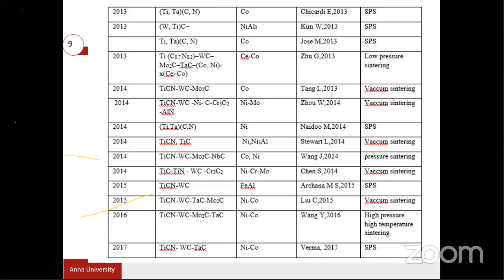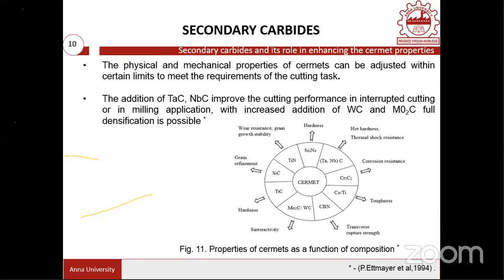Still, the problem faced by these titanium carbonitride based CERMETS is that they really suffer due to fracture toughness value. From the hardness point of view, it is showing some good improvement by adding these secondary carbides. But one thing you have to remember is that microstructural modification is necessary: you have to control the core structure, the inner rim formation and the outer rim formation, then you can play with the modification of hardness and toughness value. Here, the addition of tantalum carbide and niobium carbide really improves the cutting performance in interrupted cutting. So it can be a substitute in titanium carbonitride.